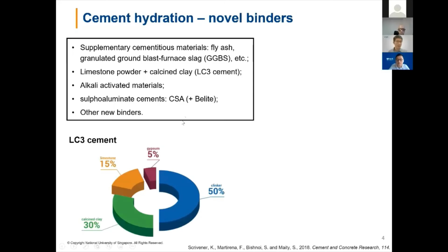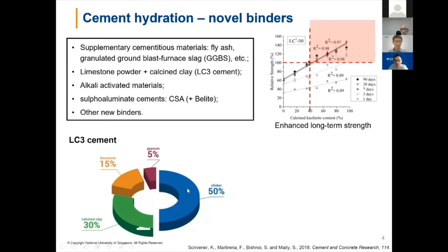Now, to give an example, let's look at the LC3 system. In this LC3 cement, we replace 50% of Portland cement clinker with calcined clay, limestone, and gypsum. Those 3 materials are conventionally considered as not reactive, okay? But we figure out that even though we replace half of the cement clinker with these non-reacting phases, we're not sacrificing the strength of cement paste too much. When the kaolinite content in the calcined clay is above 40%, we realize that the strength of the LC3 paste is already comparable or even higher than the strength of normal Portland cement.